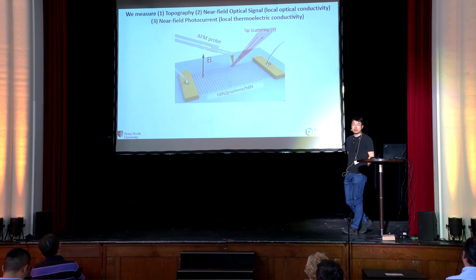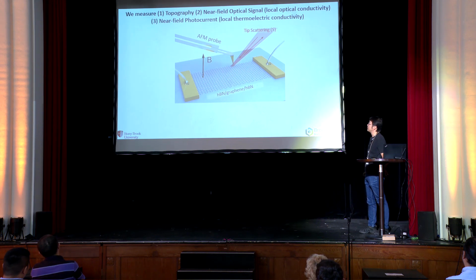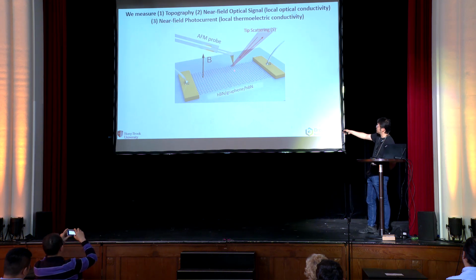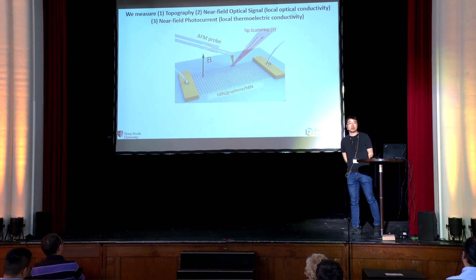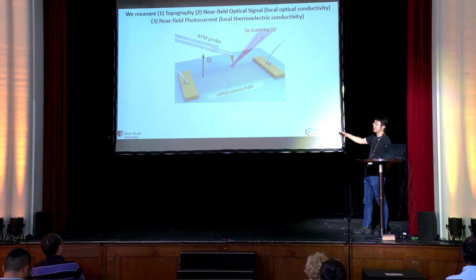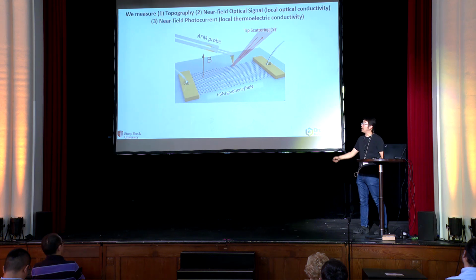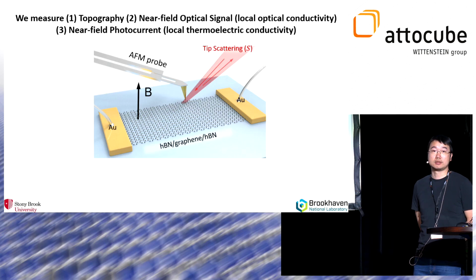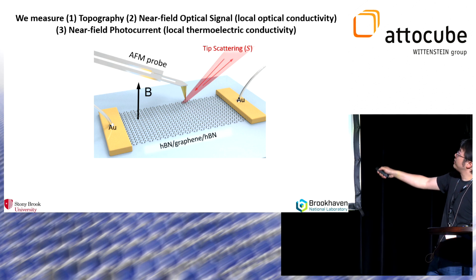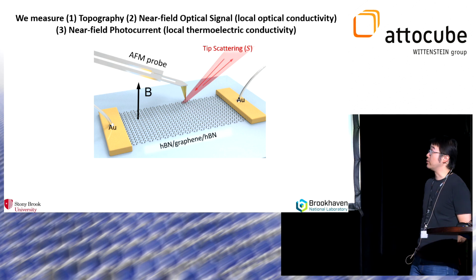So we measure 3 things with our systems. Of course, topography, right? You have the AFM, and the near field scattering signal, with which you measure the optical properties by measuring the scattered signal. You can also put electrodes on it. If Frank Koppens was here yesterday, he would have told you more about it. You can put electrodes on it and probe the so-called near field photocurrent, right? And basically the tip will locally enhance the field. In graphene in particular, this enhanced field will give you a temperature gradient locally under the tip so that you can measure the photocurrent generated in near field, okay? So we measure these 3 things simultaneously with our system.